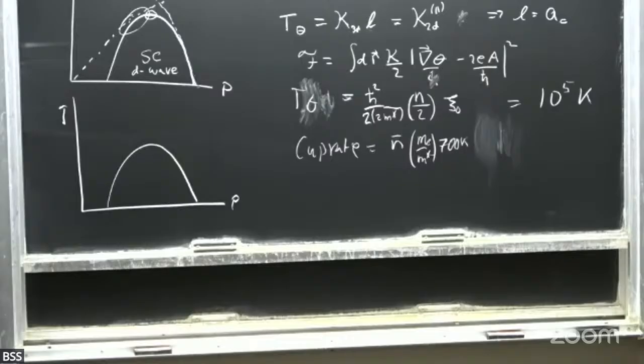Now, in a usual BCS superconductor, this isn't a problem. There is a gap that's 0 above Tc and opens as an order parameter as you go below Tc. So there's no ambiguity that this is a superconducting gap. But in the cuprates, the spectroscopy is very much more complicated, especially in the underdoped regime. There is a pseudo gap, but in the overdoped regime, there's also evidence of gaps that persist above Tc.